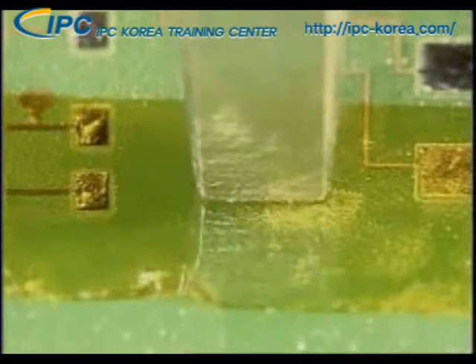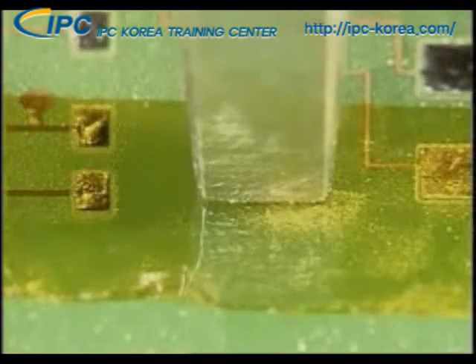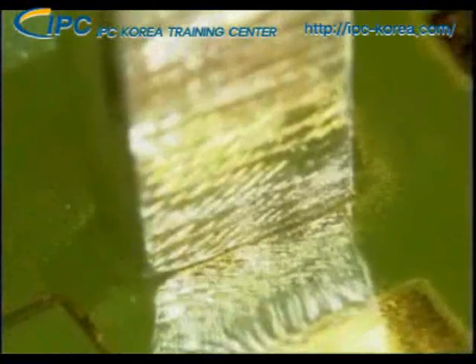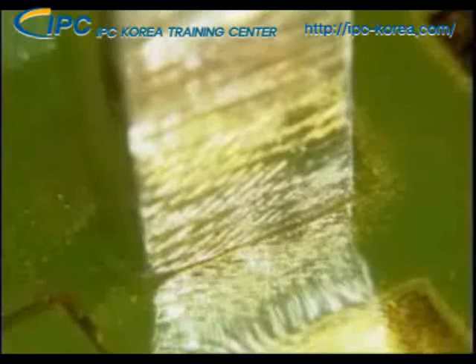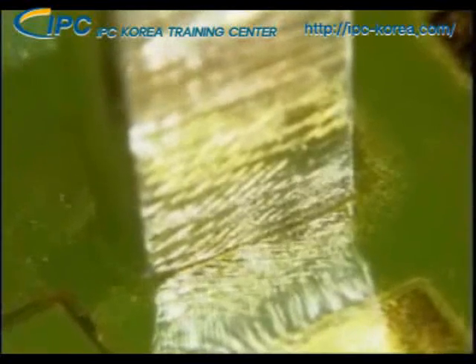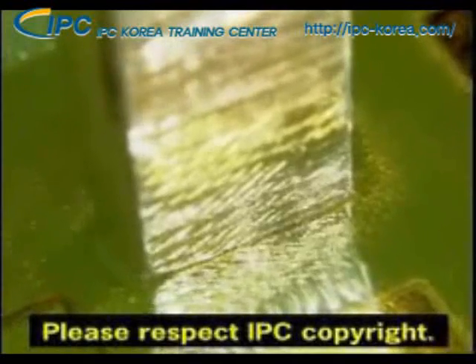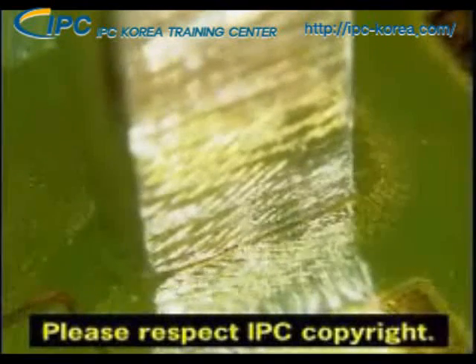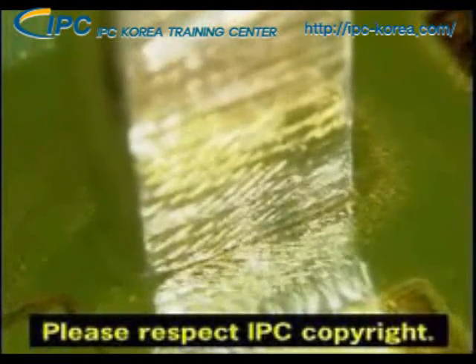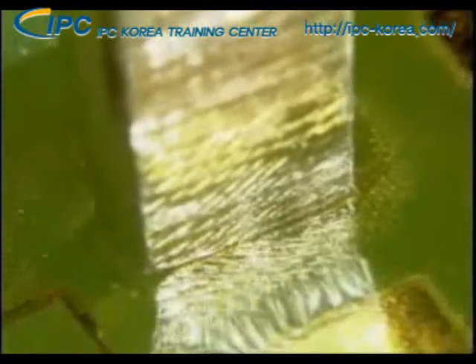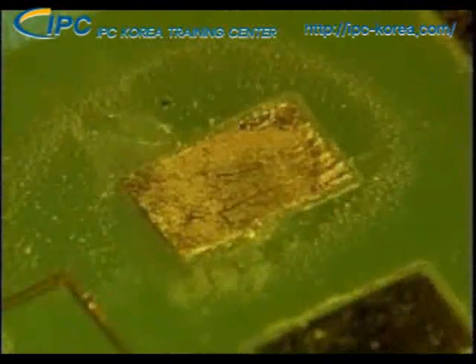Next, gently place the hot bonding tip onto the heat-resistant tape covering the land. Make sure your tip exactly covers the surface of the land while you apply the correct pressure. The heat from the tip passes through the tape and land, causing the adhesive underneath to reflow. Leave the bonding iron in place on top of the land for the full amount of time. The reflow adhesive hardens again, or cures, bonding the land to the board. Now remove the hot tip and allow the adhesive to cool.